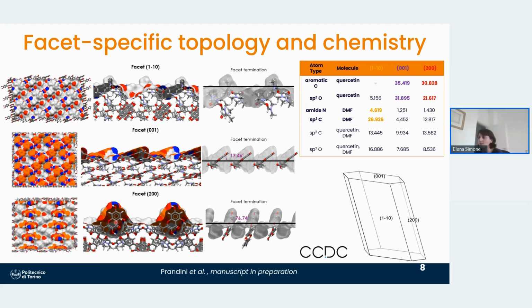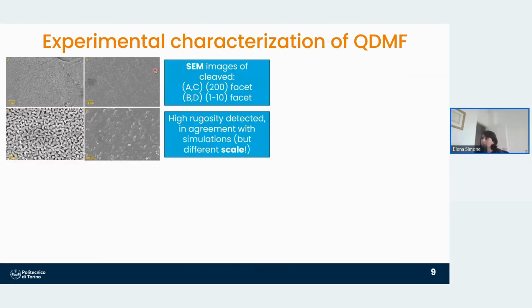So in facet 200, we can see these quercetin molecules, so those are the aromatic rings, which are almost vertically positioned compared to the facet, while those are a lot flatter in facet 001, and they are a little bit hidden within the structure in facet 1-1-0. So we tried to do some experimental validation. We tried with SEM, where we can see here the 200 facet, so the one with the vertical quercetin molecules, which is relatively rough, as you can see, compared to the 1-1-0, which was, again, relatively rough, but it wasn't really exposing those vertical molecules.